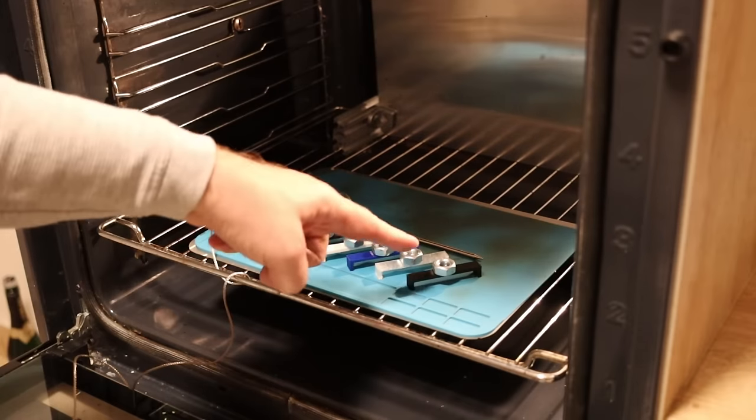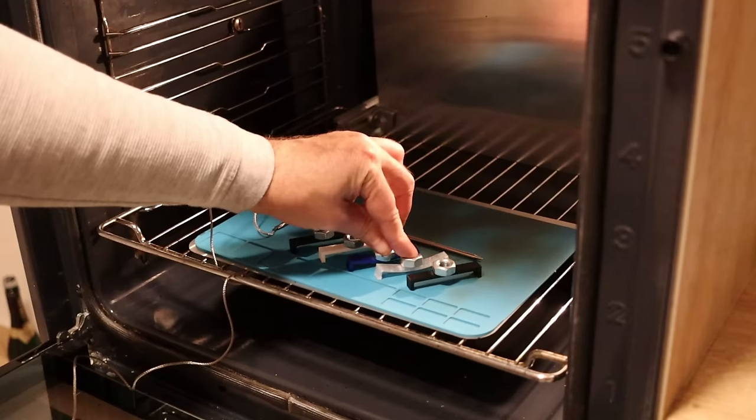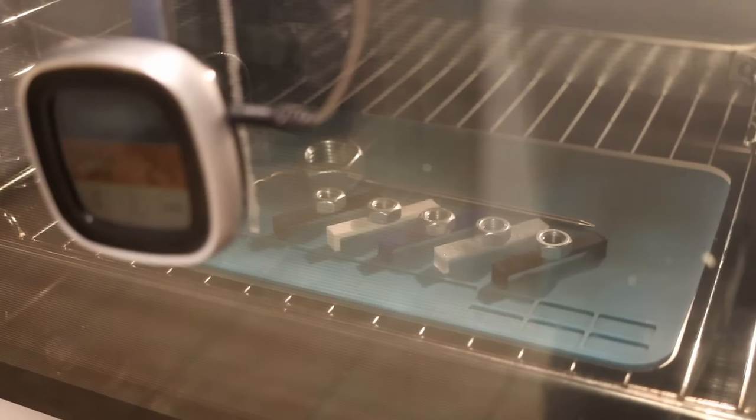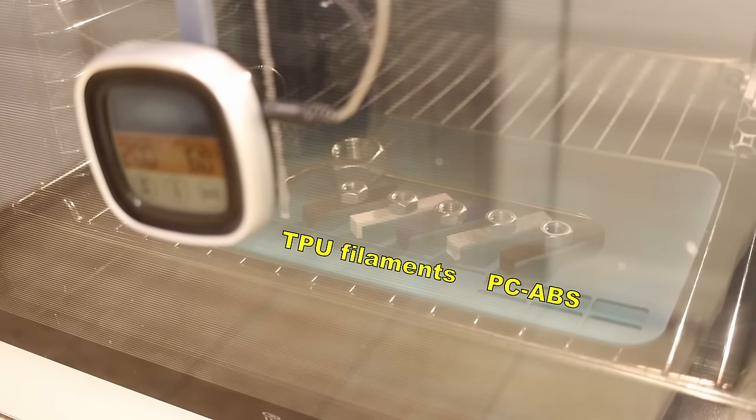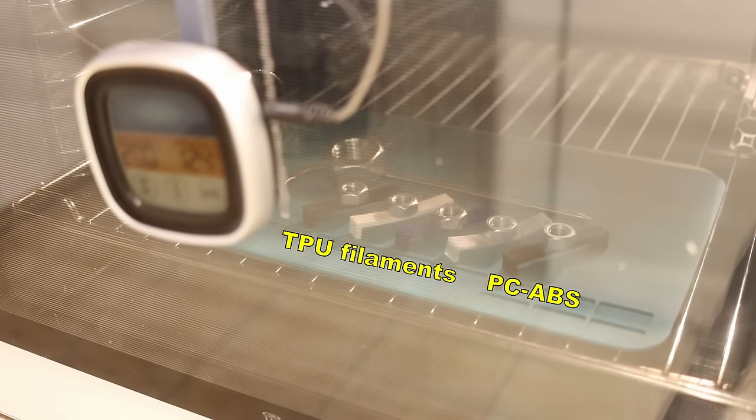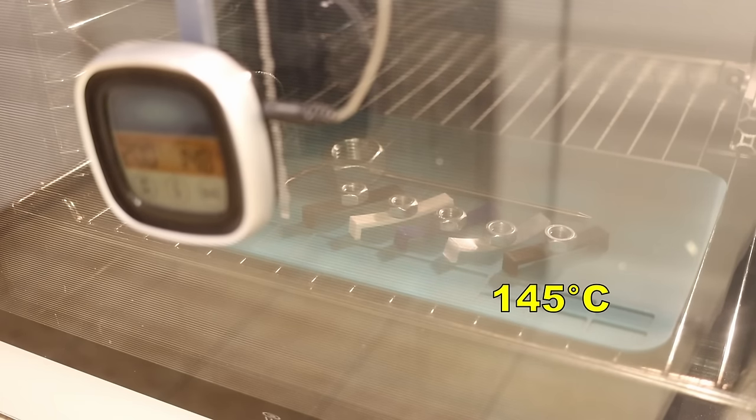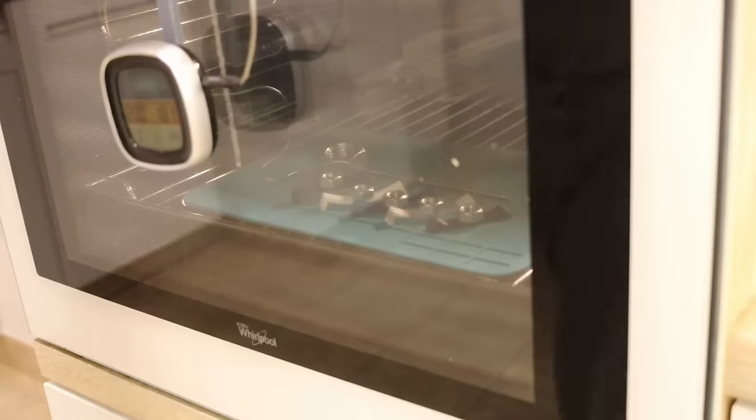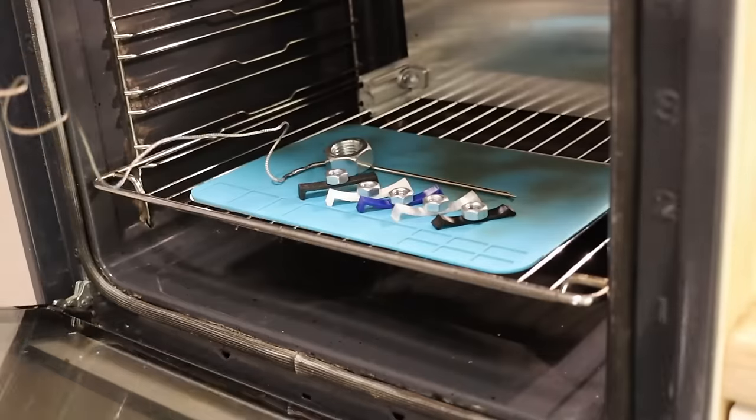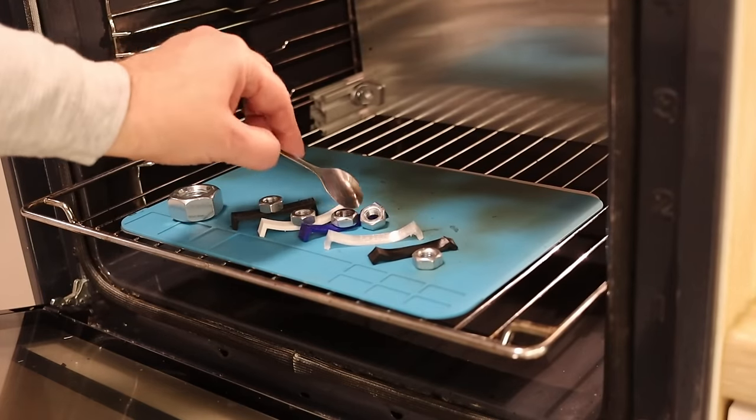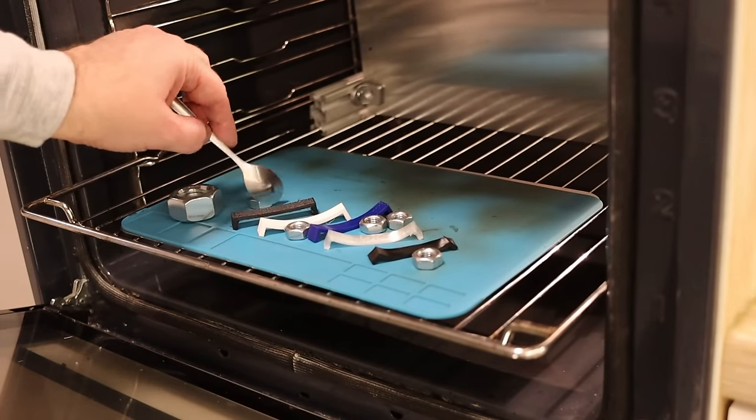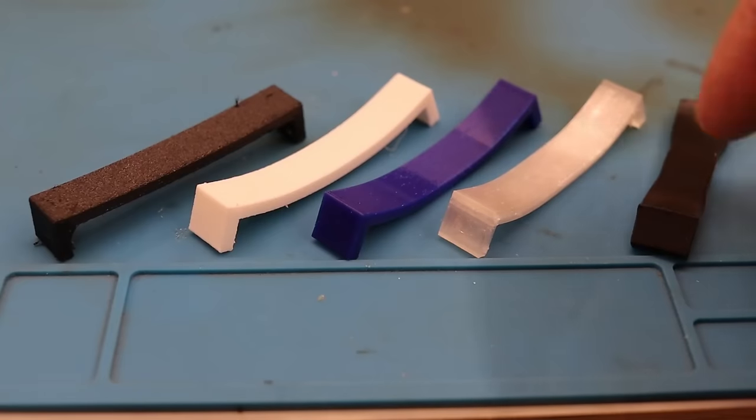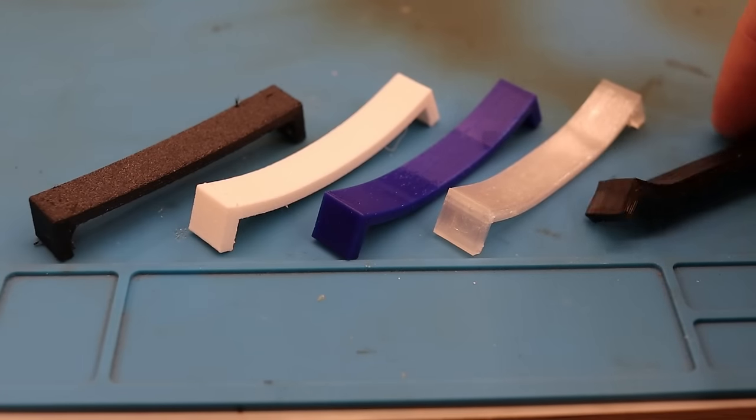The temperature test in oven. This one is the PC-ABS and I have some TPU filaments testing in progress too. And I will start here the timelapse inside the oven. And basically I try to analyze here only the PC-ABS and the first deformation I noticed at approximately 145 degrees Celsius. This is definitely much higher compared to ordinary regular ABS. I stopped the experiment on 180 degrees Celsius and of course it was deformed quite a lot but very impressive, so much better than regular ABS.